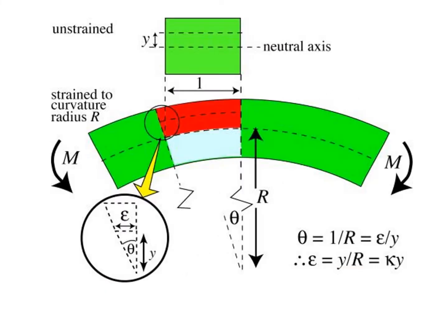If you want to calculate what the stresses are, it's very simple formulas here. The stress for anything that's a bent beam, if you like, is a function of the distance from the neutral axis and the radius of curvature. So if you look at the radius of curvature and the thickness of the specimen, assuming the neutral axis is in the middle of the specimen, one can easily calculate what the strain is.